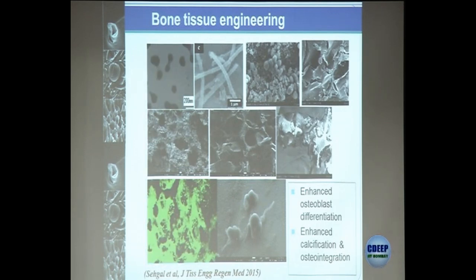And the last example is that of bone tissue engineering, where fractures which are very difficult to heal can again be treated with that in situ gel, but this time we use additional nucleating particles which are calcium phosphate based hydroxyapatite or bioglass. So in this case, over time you will have the mineralization occurring, and you have the osteoblasts or the bone cells getting stimulated, and hence difficult to heal fractures can be cured by this kind of an approach. We like to refer to this as a bone regenerative glue.